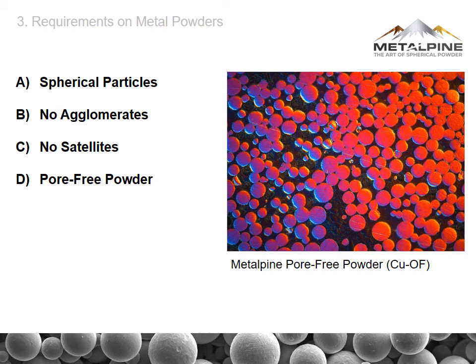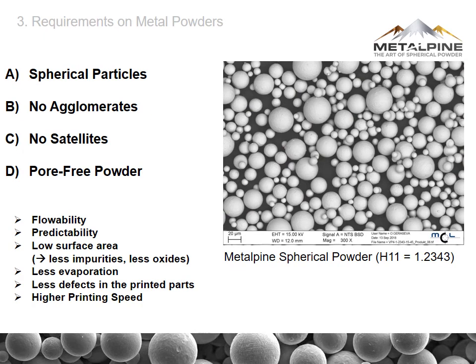Any pore in the powder will have some gas in it, and when the laser heats and melts the powder particle, the gas in the pore may puff and also increase the probability of defects in the printed part. So, to conclude: spherical particles, no agglomerates, no satellites, pore-free powder. That's what you want to achieve, to have a good flowability, a good predictability of the whole process, and at the end, fewer defects in the printed parts and a higher printing speed for your economic production.